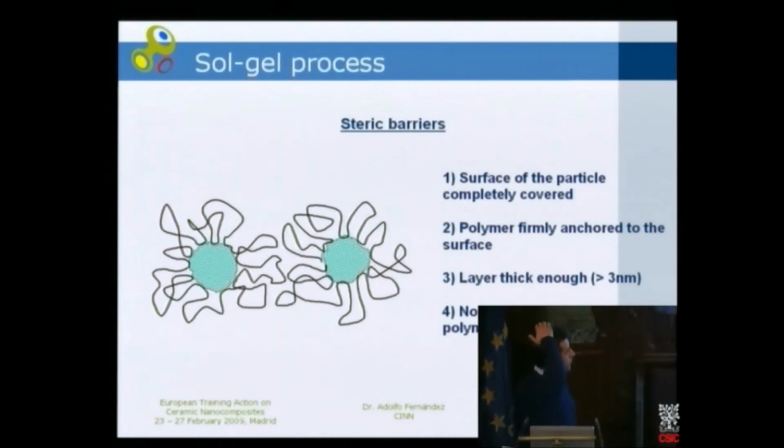And these steric barriers must accomplish several characteristics. The surface of the particle must be completely covered. And this polymer must be firmly anchored to the surface to avoid the detachment of the polymer if it happens a collision, for example. The layer must be thick enough to allow the separation of the particles, and the non-anchored portion of the polymer must be well solvated by the liquid.